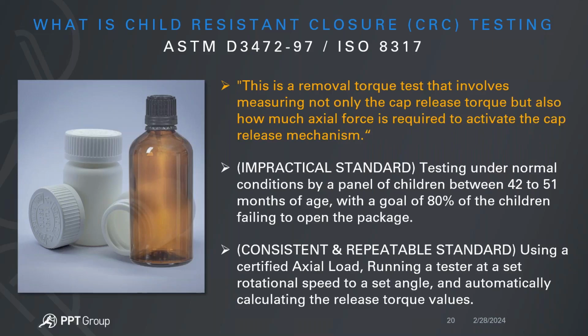Now, it's essentially simply a removal torque test that involves measuring not only the cap release torque, but also how much axial force is required to activate the cap release mechanism. So you'll find most of these containers are push and turn. You'll find this in both the medical device and the chemical industry, whether it's bleach or any dangerous chemical around the house, or sometimes even cosmetics, where we're trying to protect the little ones from having any contact with this chemical or medication. So it requires a certain amount of axial force to activate that release mechanism, and then a certain amount of release torque to actually uncap the container.